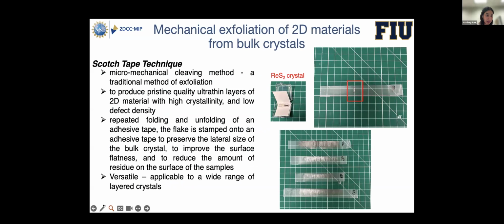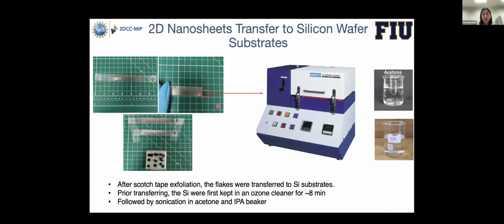And this is the ReS2 crystal which we bought, and then we used this material and the Scotch tape. We put this crystal onto the Scotch tape, and with the repeated folding and unfolding of the Scotch tape, we basically got layers all over the Scotch tape. This is the exfoliation procedure which we used, and then we wanted to transfer those exfoliated layers onto the substrates.